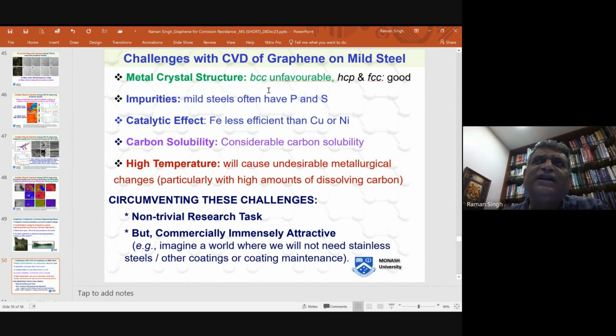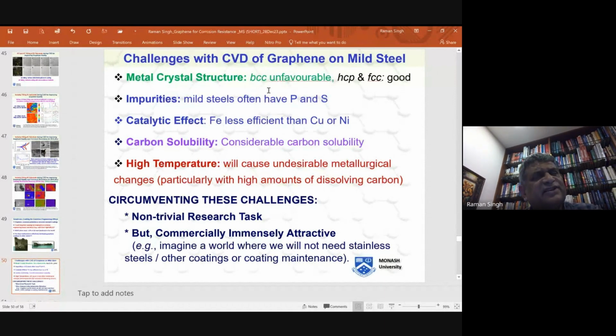So what will happen at 1000 degrees Celsius, steel will be absorbing or solubilizing quite a lot of carbon. And when you cool down, it will transform to BCC, and all of a sudden it will reject a lot of carbon because FCC has 100 times greater carbon solubility. That is a challenging situation. If you have uncontrolled release of carbon, uncontrolled diffusion of carbon to the surface, that does not meet the criteria of controlled supply for graphene development. And because of that particular reason, I'm not going through other reasons, it is a non-trivial task. It is almost impossible to develop graphene on mild steel.